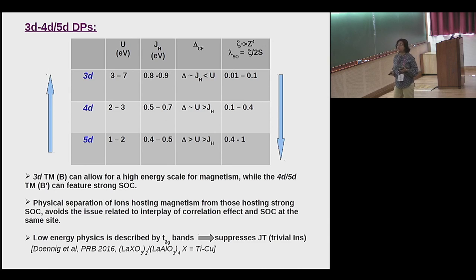And as I will try to show, this low energy physics is basically described by the octahedral crystal field split t2g bands, which are the low spin state of this 4d or 5d that heavily suppresses the Jahn-Teller distortion. That distortion has a tendency of converting this topological insulator into a trivial insulator, as was discussed in the paper by Pickett, where he took several different oxide interfaces and showed that most of them, in spite of trying very hard, turned out to be trivial insulators, because these were all eg-dominated physics that made the Jahn-Teller distortion very strong.